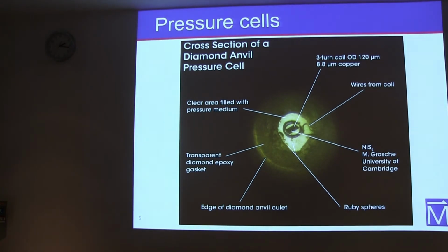This is what a typical setting looks like. This rim here is the culet of the diamond, the tip of the diamond. The dimension here would be 500 microns. This mostly transparent part is the gasket to hold the pressure medium, and in our case, we use non-metallic gaskets, a mixture of diamond powder and epoxy. The sample is located here in the center, and this is the pickup coil that we use to make the measurements, and I'll talk about this later. We measure pressure by looking at the fluorescence of ruby, so I place several rubies inside the sample chamber.